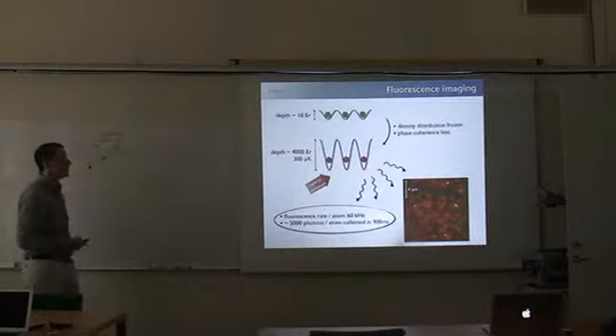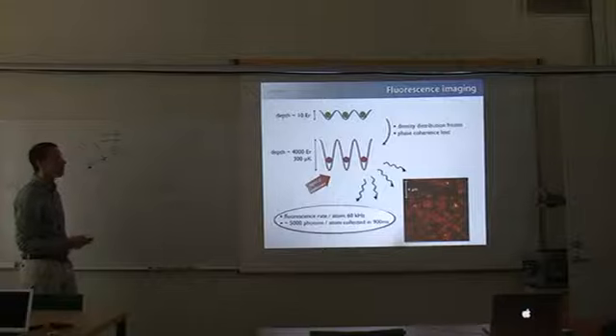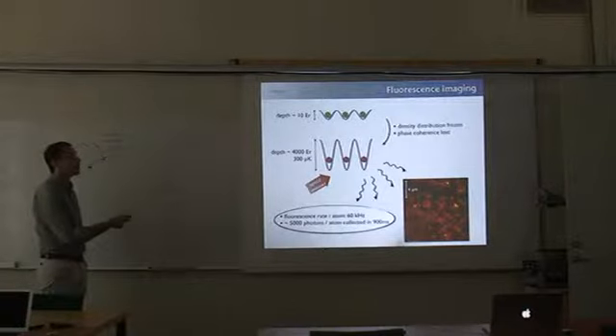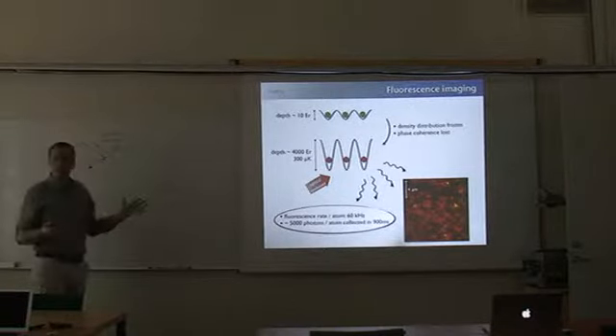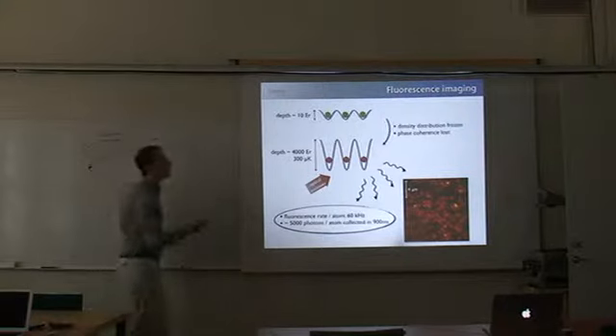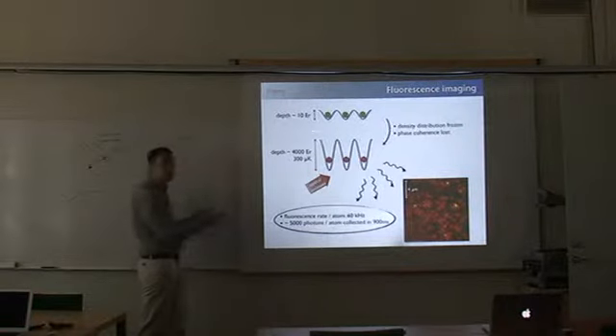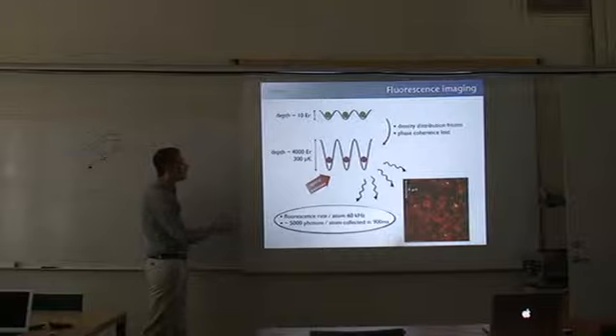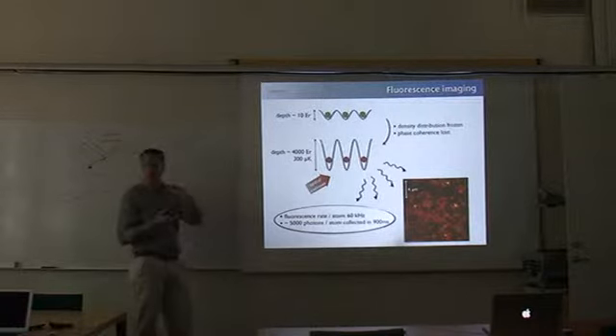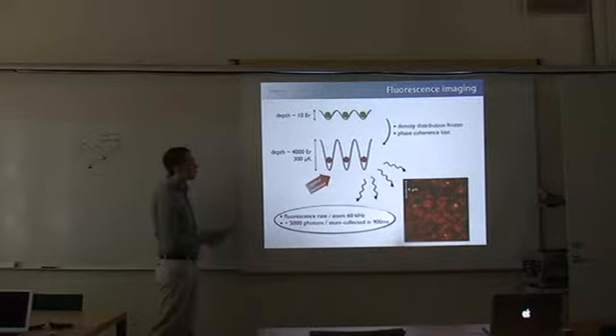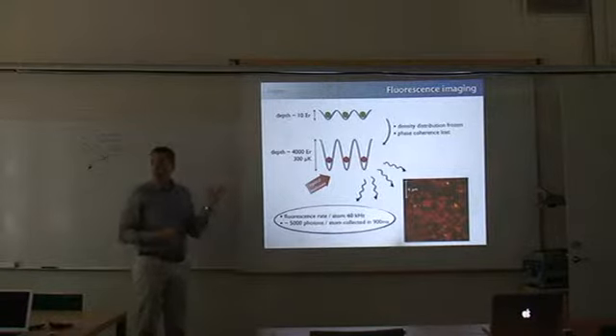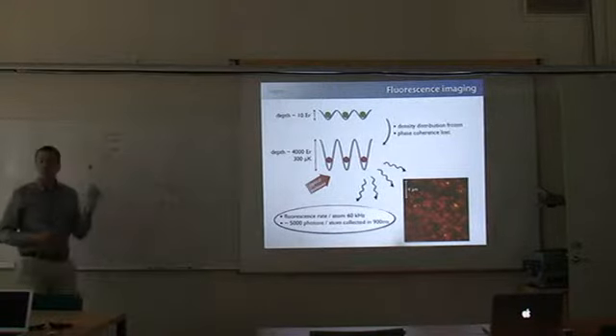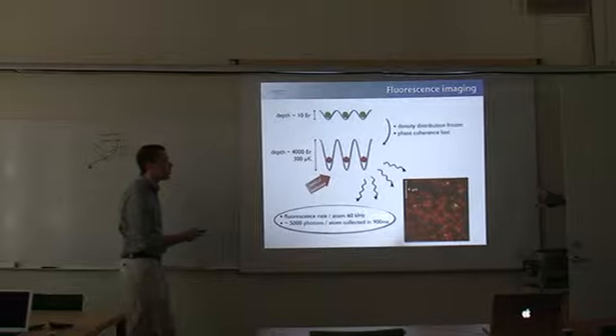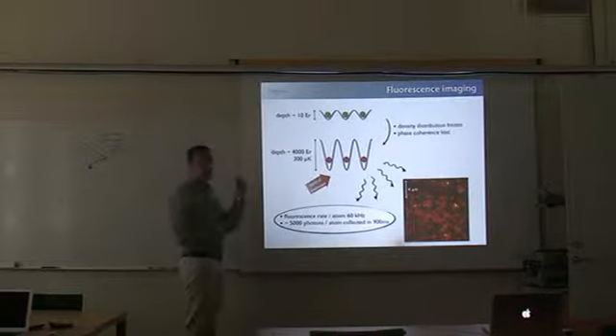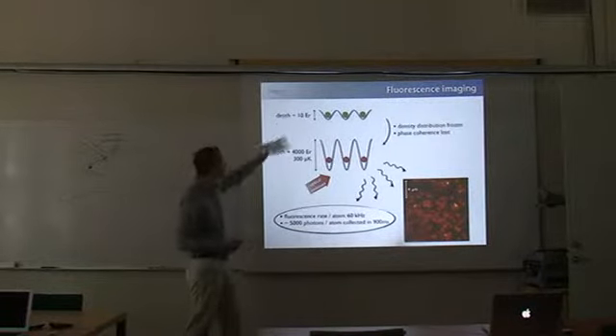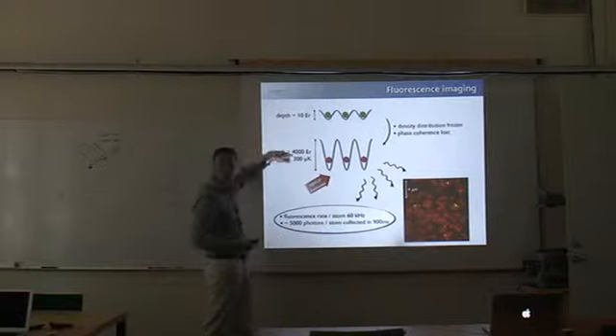Okay, so how do we proceed in the experiments? In the experiments we typically do the following. We do our many-body physics experiments at shallow lattice depths, let's say around 10 recoil, something like that, where we prepare the many-body states that we want to look at. Then we rapidly jump to a dramatically deeper lattice. This is just to make sure that we can hold on to the atoms while we illuminate them, while we make them fluoresce. Because we're scattering a lot of photons off them, we're heating them a lot, and in order to not make them escape, the potential has to be very deep in which we hold them. So we jump from a 10 recoil lattice to a 4,000 recoil lattice.